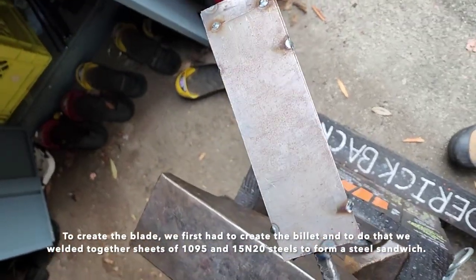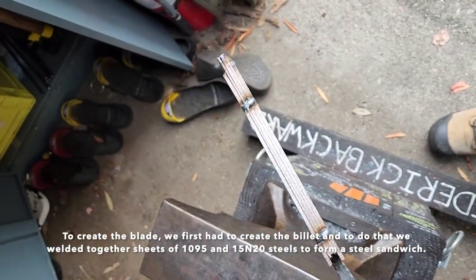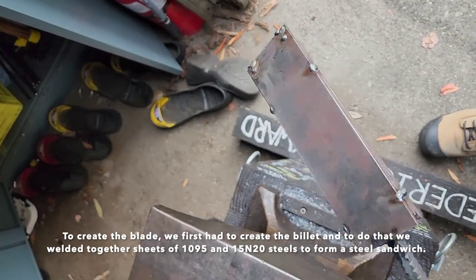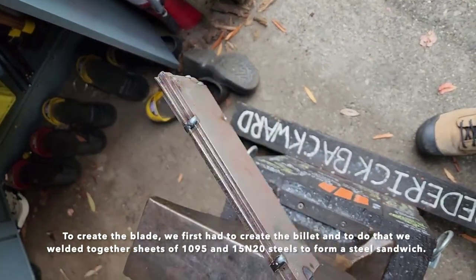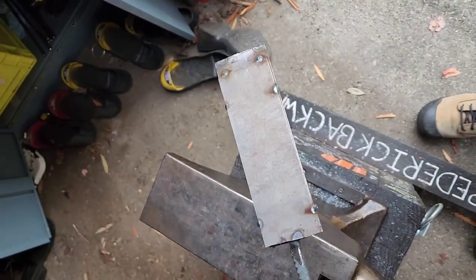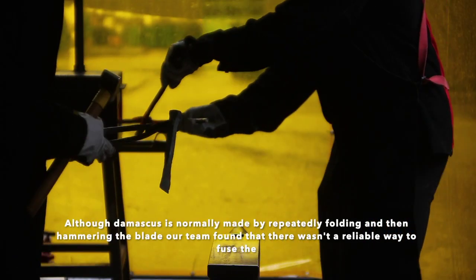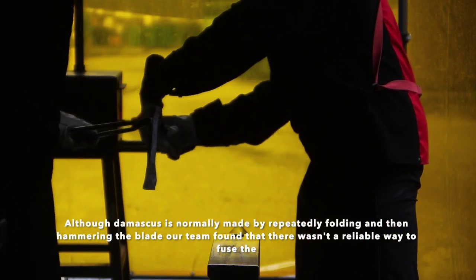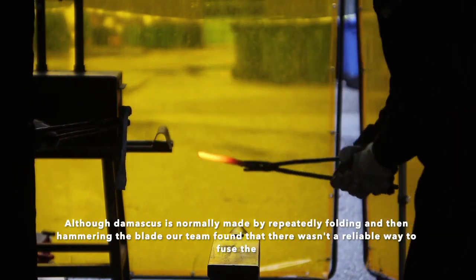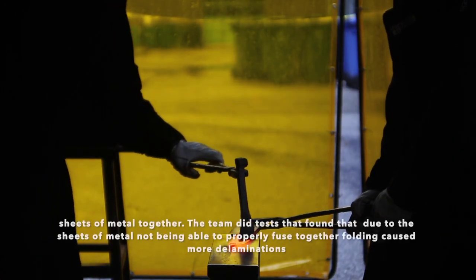To create the blade, we first had to create the billet, and to do that, we welded together sheets of 1095 and 15N20 steels to form a steel sandwich. Although Damascus is normally made by repeatedly folding and then hammering the blade, our team found that there wasn't really a reliable way to fuse the sheets of metal together.